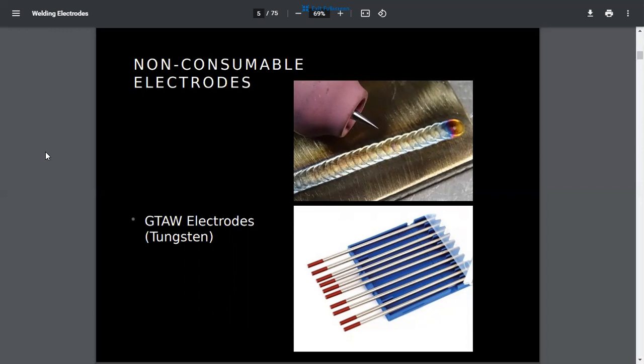So with tungsten, if you end up sticking that tip in there, you break the tip off in the puddle, and that gets x-rayed, it's going to glow bright white like a star in the middle of your weld, just because the density of tungsten is so heavy. That is definitely not something we want. So we don't want to touch or contact the tip of that electrode to our puddle at all.